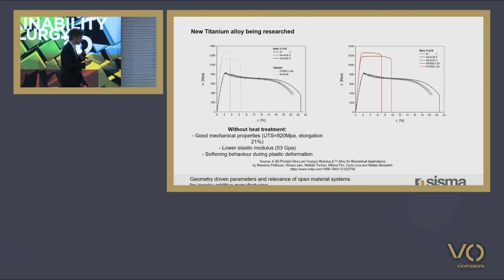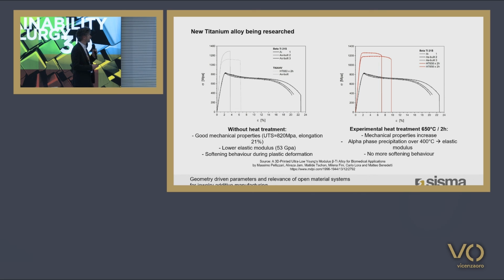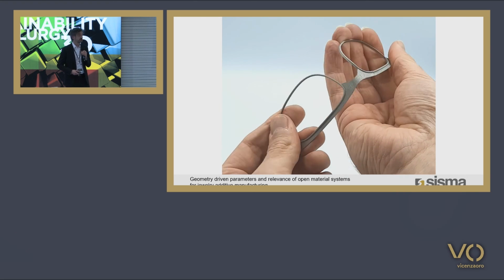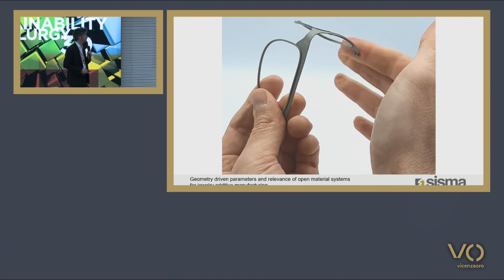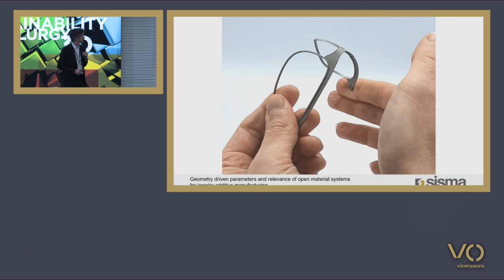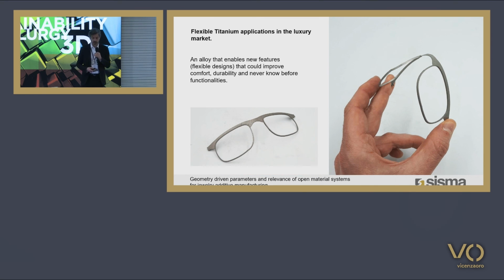Without heat treatment, we see that elongation is quite impressive. And with a simple heat treatment at only 650 degrees Celsius, it could reach and outperform titanium grade 23 in many ways. So this is an example of what can be done with this new alloy. Of course, the first application that came to our mind was the eyewear industry. It's an almost unbreakable material, but we think that the possibility of new features like flexible designs in jewelry additive manufacturing could make this a really interesting material.